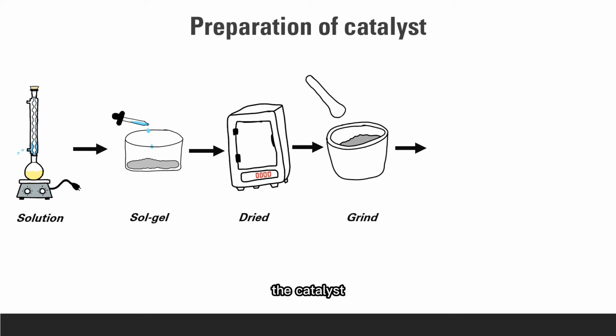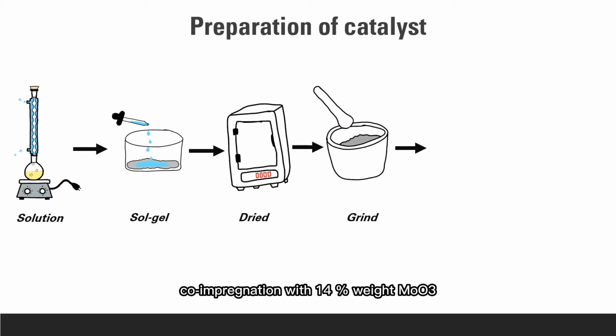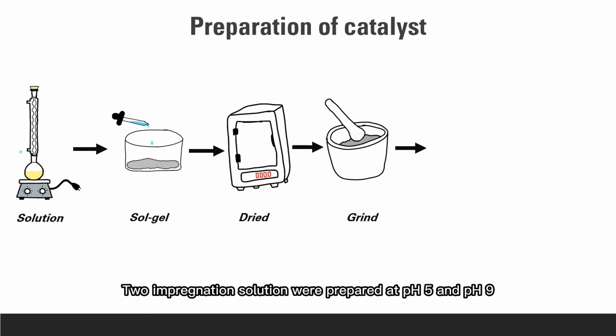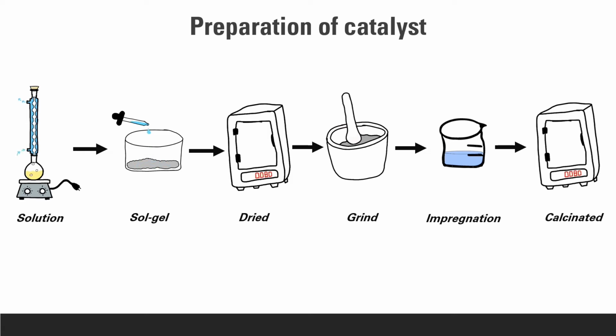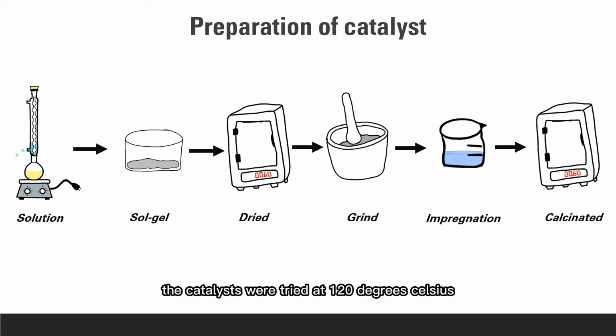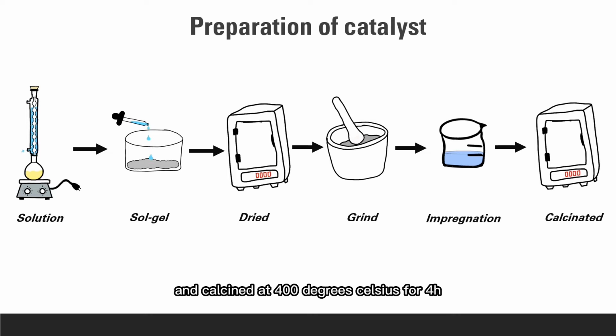The catalysts were prepared by wetness co-impregnation with 14% weight molybdenum trioxide. Two impregnation solutions were prepared at pH 5 and pH 9. The catalysts were dried at 120 degrees Celsius and calcined at 400 degrees Celsius for 4 hours.